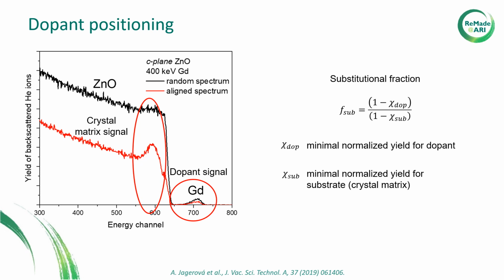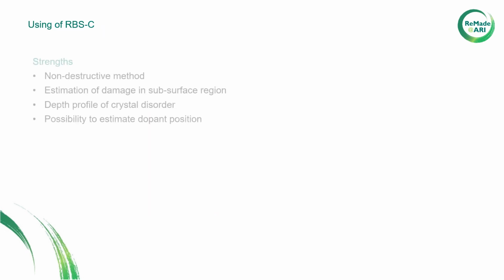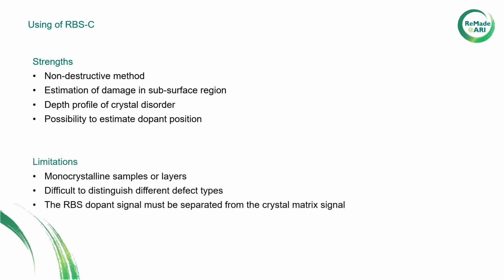This can be done by comparing the minimum normalized yield estimated for the dopant RBS signal and for the corresponding signal of the crystal matrix. The biggest advantage of this method is that it is considered a non-destructive method. Additionally, we have information about crystal disorder and its distribution in the subsurface region. It also offers direct information about dopant position in the crystal matrix. On the other side, this method can be successfully applied only for monocrystalline materials, and it is complicated to distinguish between individual defect types. Also, the positioning of dopants and impurities can be done only when the signal of the dopant is separated from the crystal matrix.